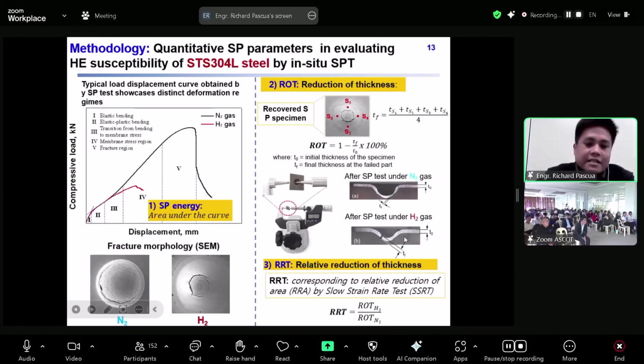Lastly, the relative reduction of thickness is derived from the ratio of the reduction of thickness under the hydrogen environment and the nitrogen environment. This parameter will be used to compare with the other method, which is the relative reduction of area, or RRA, by the slow strain rate test, or SSRT.